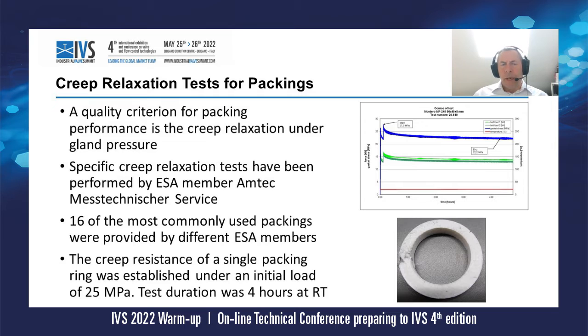Another quality criterion for packing performance is the creep relaxation under gland pressure. Unfortunately, for specific packings or packing materials, there were no specific creep relaxation values available. So the packing division decided to run their own test, and one of our members is the company Amtec Messtechnischer Service, who specialize in testing of packings, gaskets, as well as valves. So we set up a test, and 16 of the most commonly used packing materials were defined and provided by different E.S.A. members.